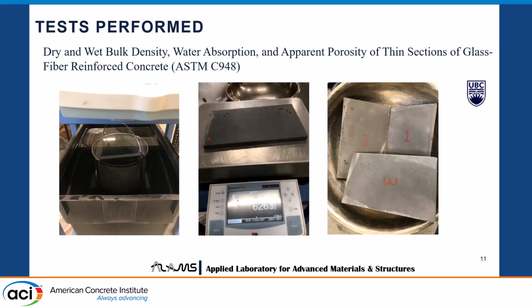So regarding the tests, GFRC has some designated tests prescribed by ASTM. So we try to do those tests. So this is the test ASTM C948, which is for thin sections of GFRC. And this is dry and wet bulk density, water absorption, and apparent porosity test. So we did this one.